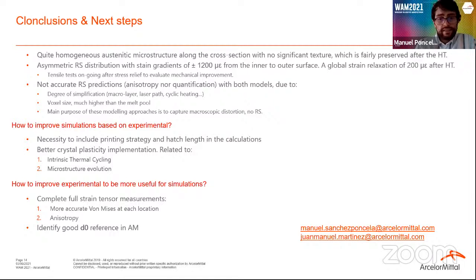We compare the experimental results with two modeling approaches, and none of them predict accurately these stresses. This is because, first, of the degree of simplification, the voxel size of the mesh that is much bigger than the melt pool, and also because at the end of the day, the main purpose of both models is to predict the macroscopic distortion of the part, and they do it right.